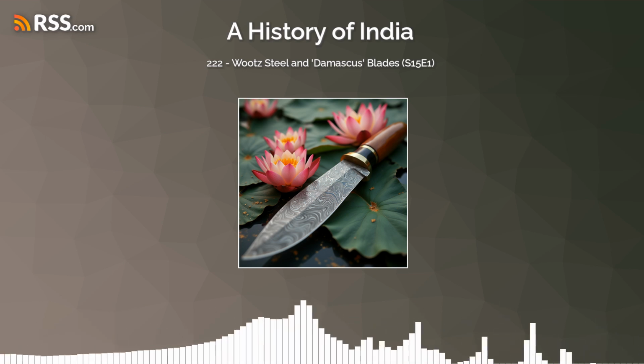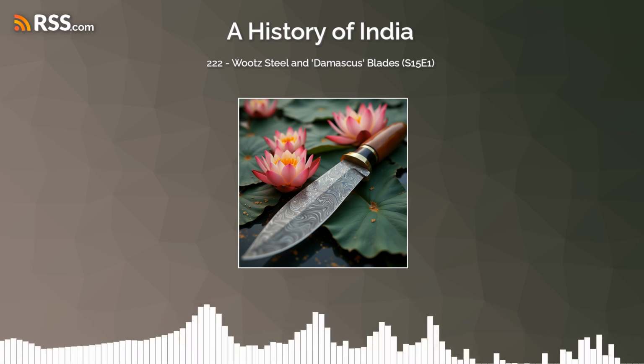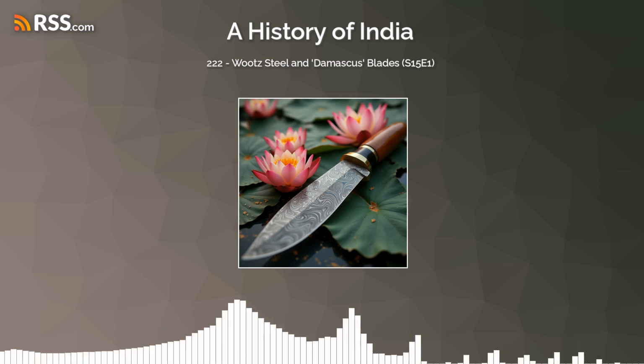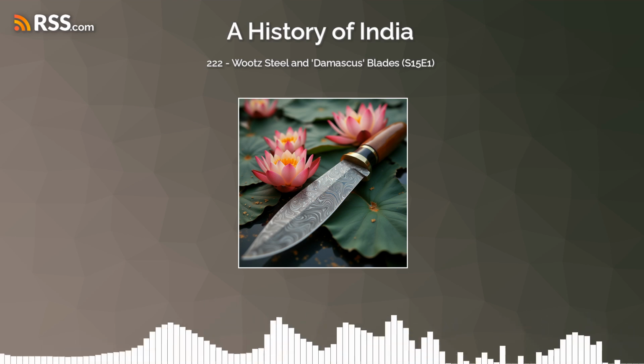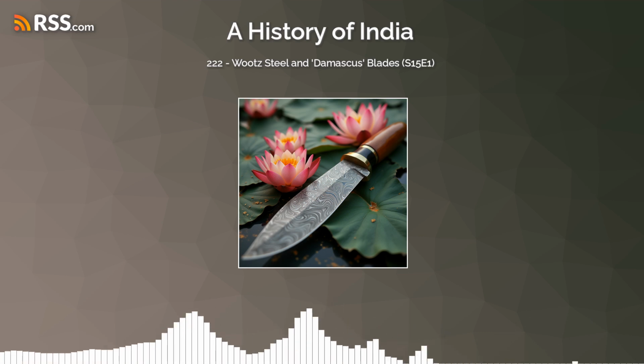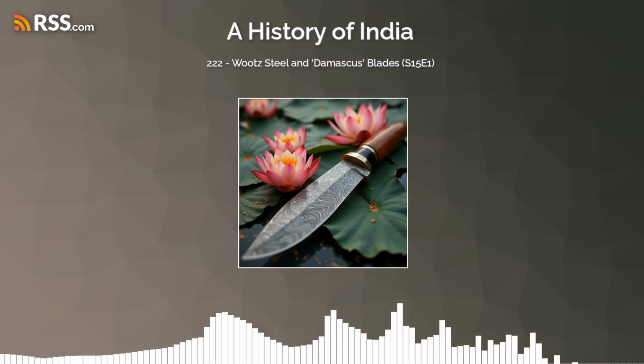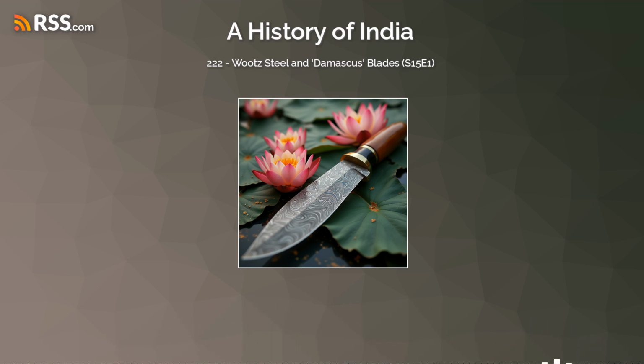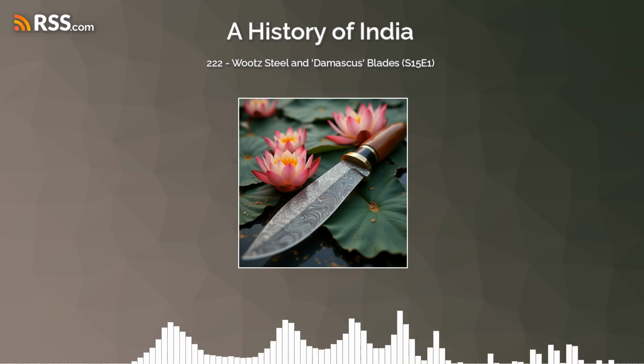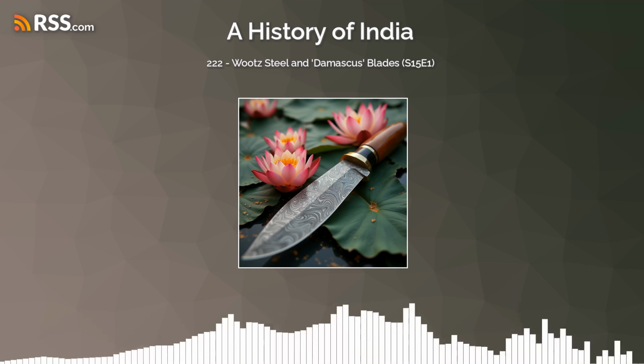Absolutely critical. Too little vanadium or molybdenum, and the pattern would be weak or cloudy. Too much, and the ingot might just crack during cooling or forging, making it totally useless. It points to this amazing level of empirical control they achieved long before anyone understood the underlying chemistry. Incredible. What else went into the crucible?